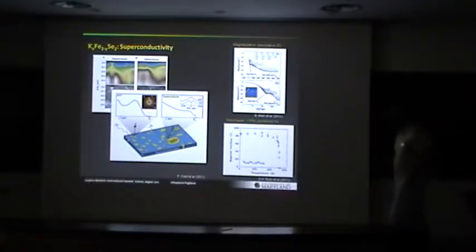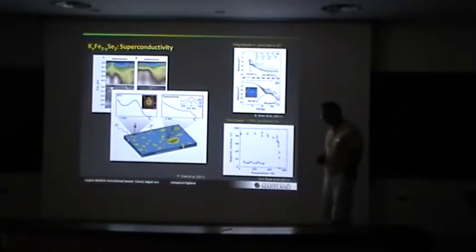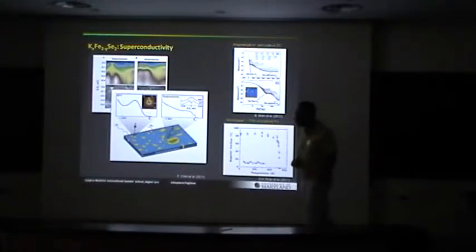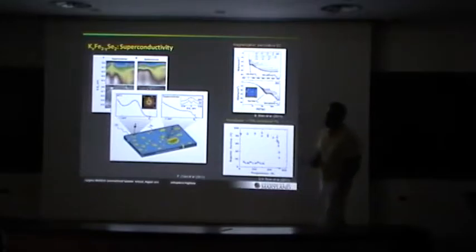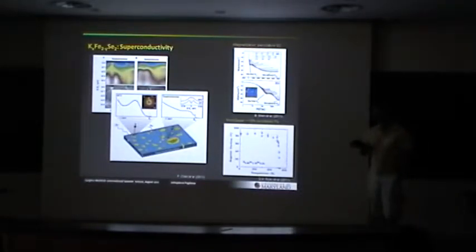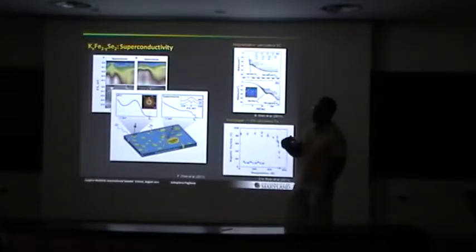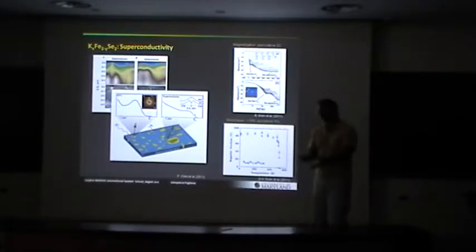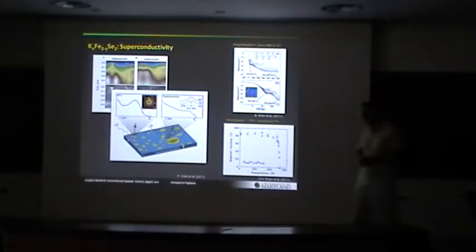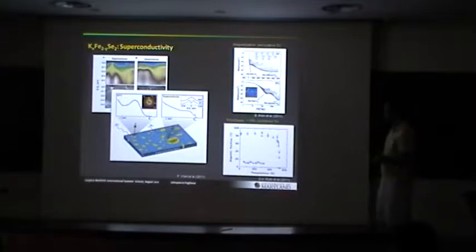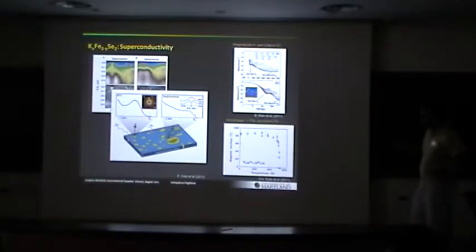But then that is completely different from what we said from the diamagnetism. You were telling us that diamagnetism is not... Yeah, but you know, as you know, it's very easy to see 100% diamagnetism in a non-100% superconductor. The easiest case is coat a piece of gold with lead. Then you do a real measurement. Yeah. Okay, and of course the screening fractions in diamagnetic measurements are estimates based on how well you know the volume and so on.